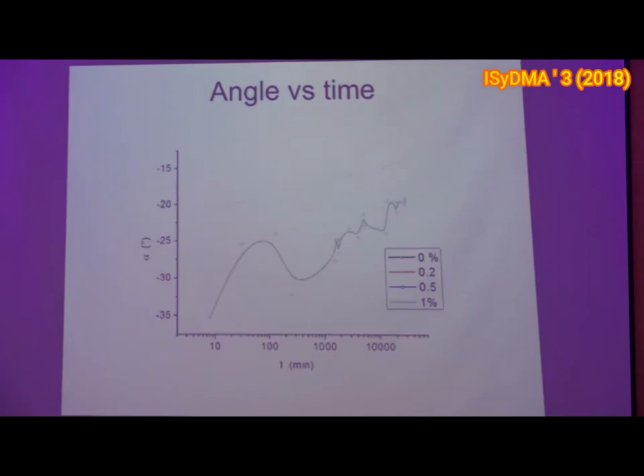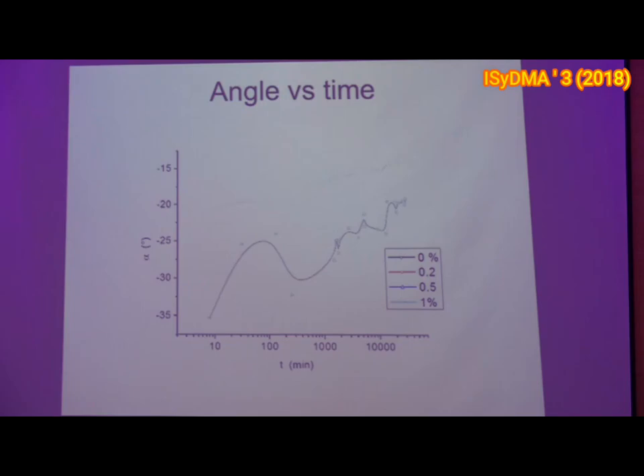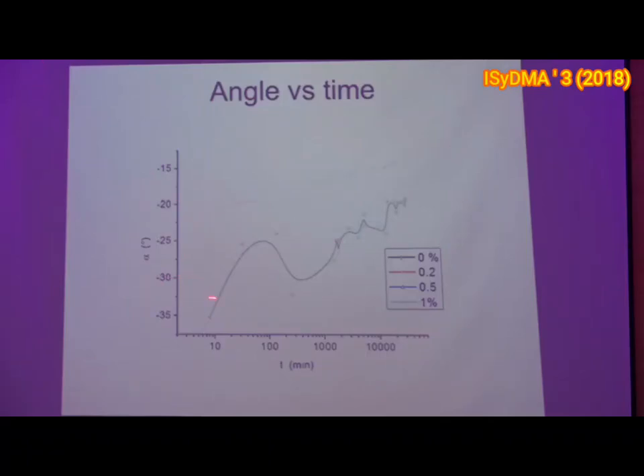Then here we are just seeing what happens with this angle, again with time, but this is the same curve, okay? This is the normal cement that we have. Here it's difficult to see, but it is what happens when we put these polypyrrole particles inside the cement. That is, when we do that, this angle changes a lot, and we have a cement that is more homogeneous because this angle is really smaller than this one. That is, we can see how the cure of the cement is going with time.